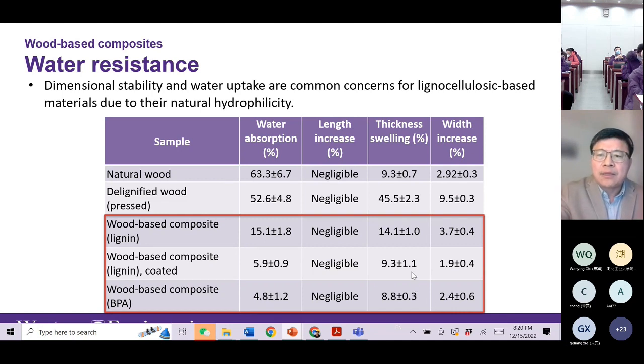And the thickness swelling is also controlled to a very low level. The width increase, which is how much expansion of the wood, is also controlled at a very low level. So we can make this wood composite highly resistant to water.